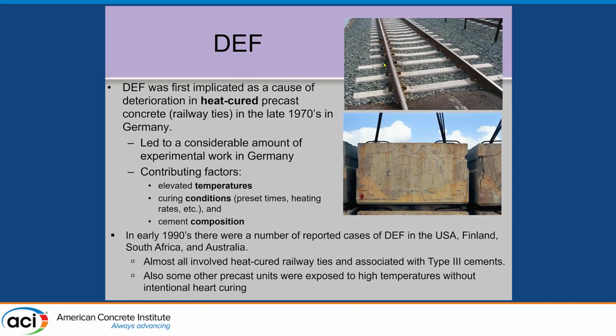And it started with railway ties. First mentioned in the 1970s in Germany, concrete railway ties that were heat-cured precast ties started to crack up and lose their pre-stress. And it was related to the elevated temperatures, maybe curing conditions, cement composition. And then there were other cases of DEF reported in various places, including US, Canada, Finland, South Africa, and Australia. And most of these were associated with type 3 or higher strength cements.